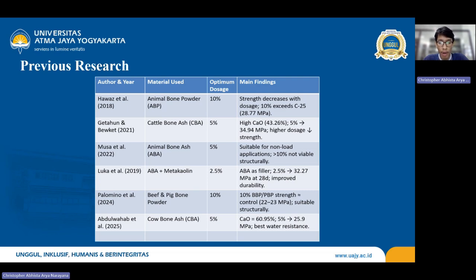in which they used a combination of animal bone ash and metakaolin with an optimum dosage of 2.5%, where the animal bone ash acts as a filler, in which 32.27 MPa at 28 days can be achieved, and it also improves the concrete durability. The fifth is Palomino et al. in 2024, in which they used a combination of pig bone powder with an optimum substitution level of 10%. As a finding, with 10% substitution, it can reach the control strength, which is suitable structurally.